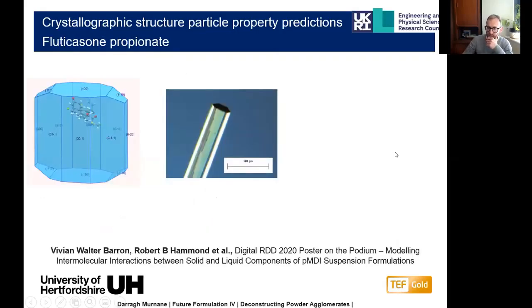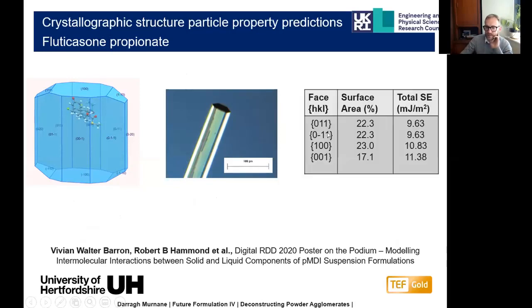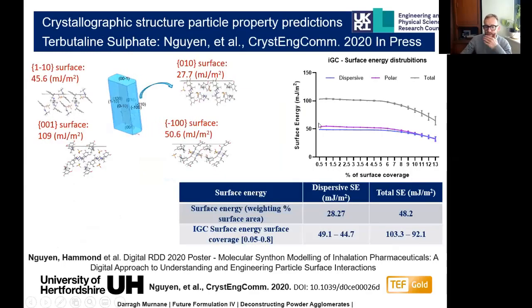Vivian presented just earlier on in the poster session his modelling on fluticasone propionate, which has been used to predict the crystal interfaces of the drug crystal, this fluticasone propionate drug crystal, and also to work out the surface energy contributions from that. We've also done the work, and I'm zooming over this obviously, which doesn't do any justice to the volume of work which the scientists and the PDRAs have done. He undertook a crystallization experiment and analysis on terbutaline sulfate. This is the second drug which we use in our systems, and has been able to calculate out the surface energies, dispersive surface energies, and surface energy distributions.